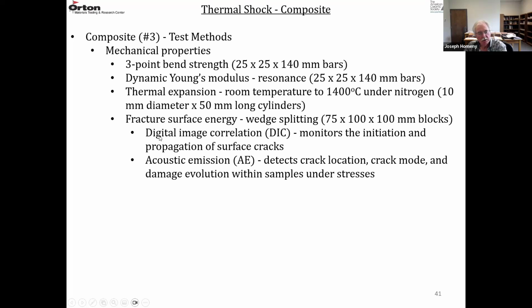But they used digital image correlation. So they monitored the initiation and propagation of the cracks on the surfaces of the wedge splitting block. And they also used acoustic emission, and that detects the crack location, the crack mode, and the damage evolution as the sample is loaded and as the crack propagates.